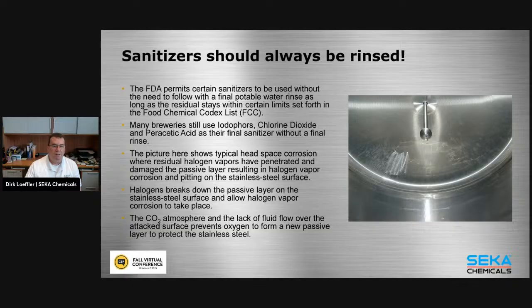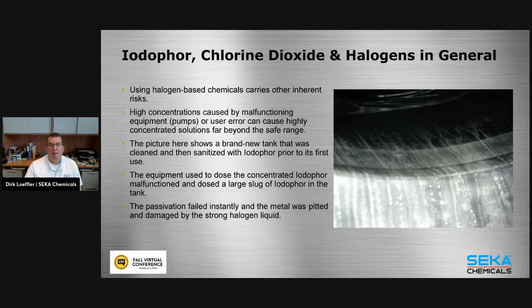In addition, the CO2 atmosphere and the lack of oxygen further make our passive layer weak. So now we have a halogen, a weak passive layer, and almost ideal conditions for the halogens to break down the passive layer and start going after our stainless steel. I generally discourage the use of halogens as sanitizers in the first place. When I first came here in the early 90s, iodophore was everywhere. Everybody was using iodophore as their primary sanitizer, and then it went more and more toward peracetic acid.